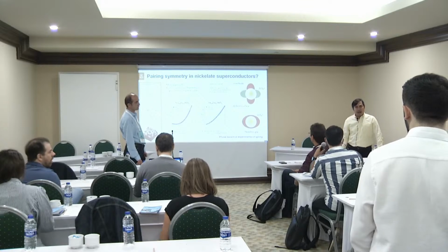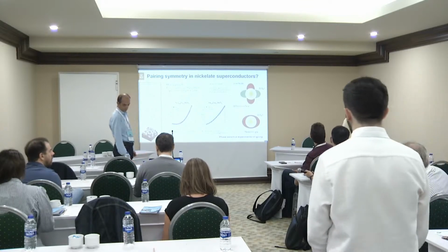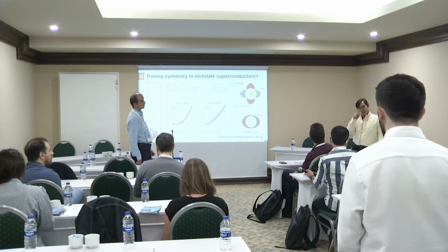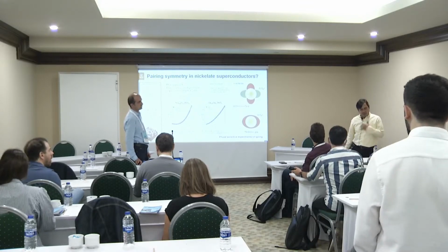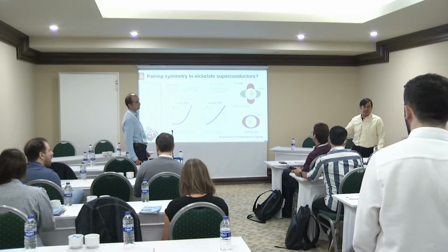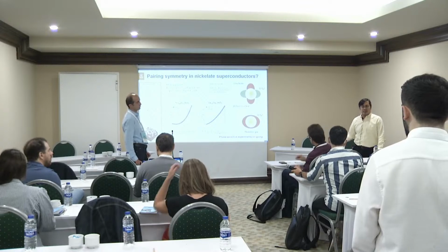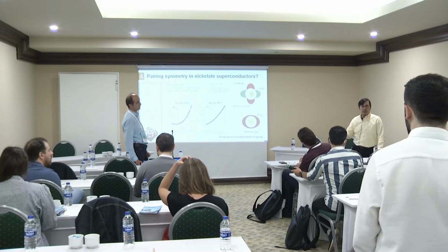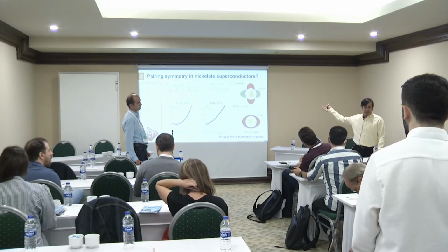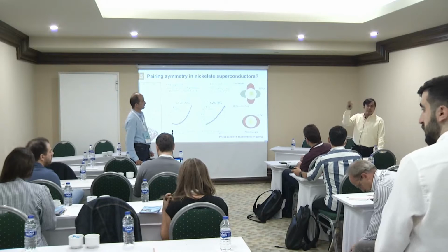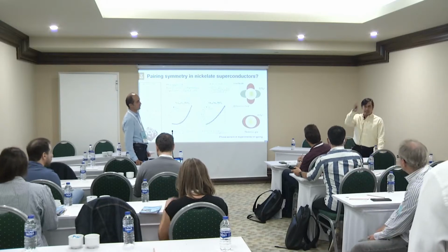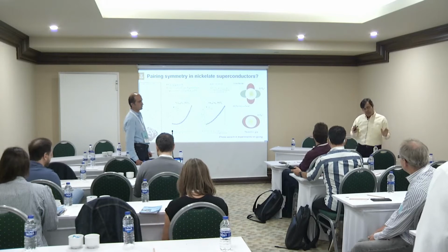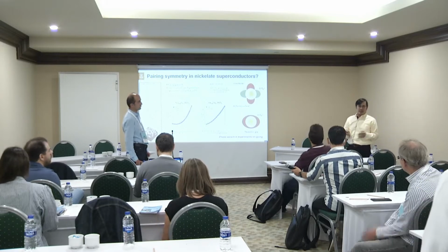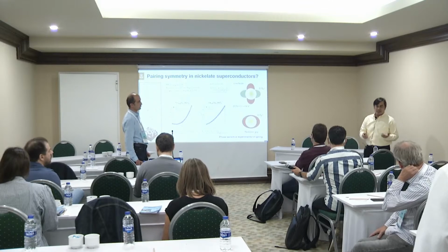I don't think there is a concrete proof that the dip in the superconducting dome is an intrinsic thing. Personally, I believe it's more like sample-to-sample quality variation in this case. We have reproduced the phase diagram with better quality samples. So the one that I showed is really the first one, and we don't have that dip anymore. So it's really just a single dome. There might be, I don't know, but at least there is no concrete proof that it is really intrinsic in the case of nickelate.